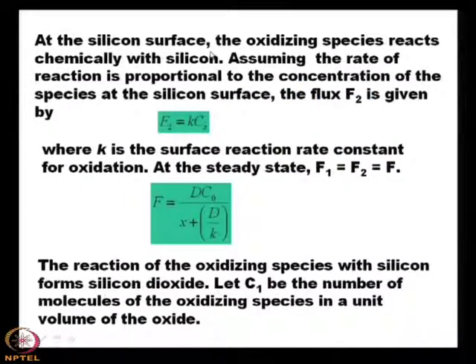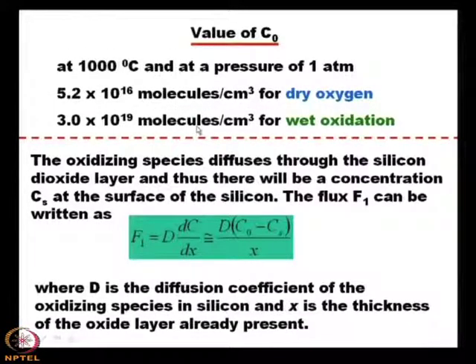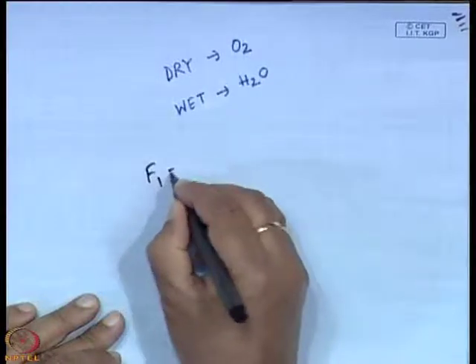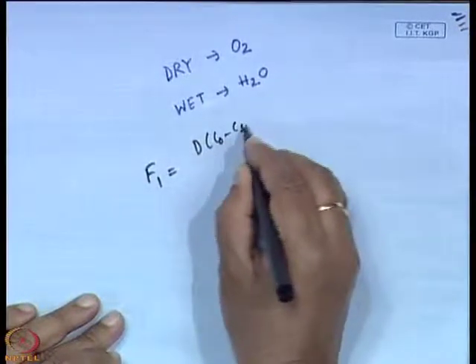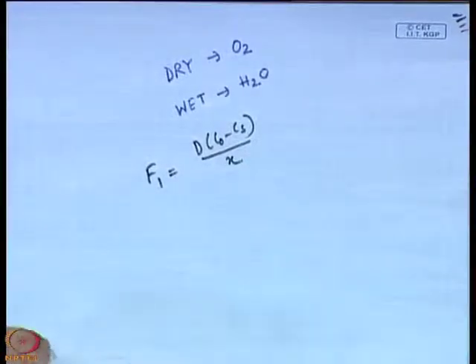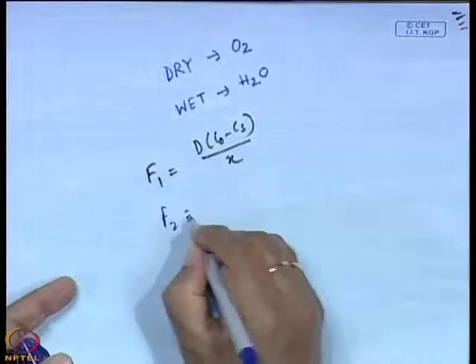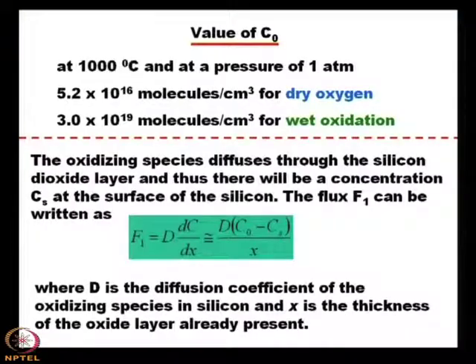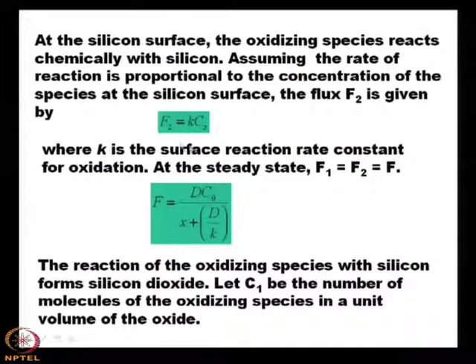At the silicon surface, the oxidizing species reacts chemically with silicon, assuming the rate of reaction is proportional to the concentration of the species at the silicon surface. The flux F2 is given by F2 equals K into Cs. So, what we find is that first F1, which we can write as D of C0 minus Cs by x, and F2, which we can write as K into Cs. This Cs is the concentration at the surface of the silicon. Then what is K? K is the surface reaction rate constant for oxidation.